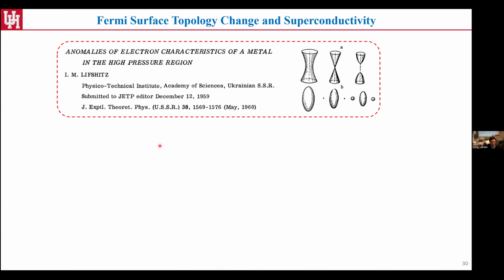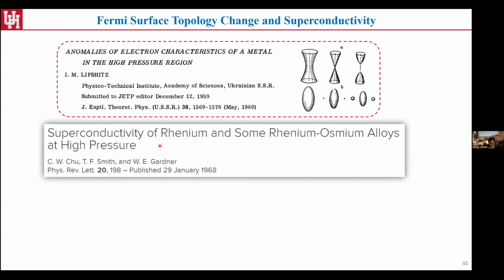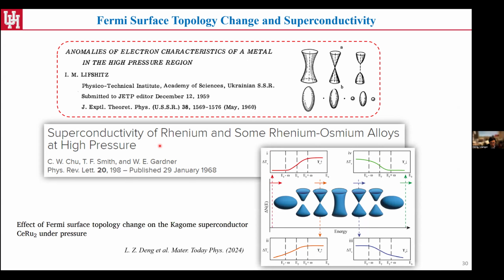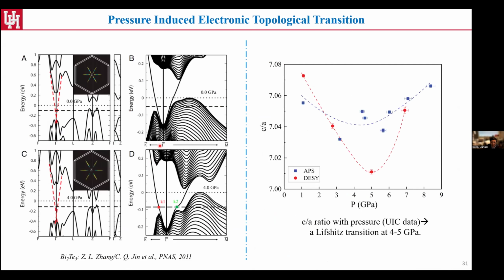So the very famous Lifshitz transition was brought up as early as the 1960s, and later on, including ourselves, many people working on high pressure found that under high pressure you could introduce this type of topological change on the Fermi surface, which correlates to the increase or decrease of density of states. Then as a result, we're tuning the superconductivity. So that's why we look into this perspective, whether we can get some experimental or theoretical evidence.